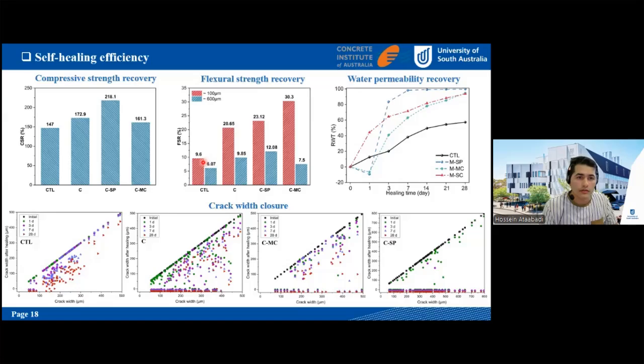So in terms of results, this is the compressive strength recovery. So we had three mixes with the capsules and one control sample. It obviously shows that the samples with the capsules recover the strength much more than the control samples. It's showing that it can generate healing products that can fill the cracks and densify the structure. Here is for the compression test, and this graph is for the flexure test.